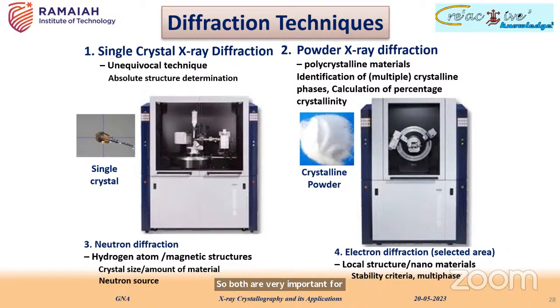In the single crystal diffraction technique, we use a tiny single crystal, which is just a millimeter or even less in size. And in the powder diffraction technique, we use polycrystalline material. For single crystals, in sample preparation you need to grow a defect-free crystal by using a technique called slow evaporation. In the powder method, you can use the sample as it is, but it should be in the form of a fine powder.